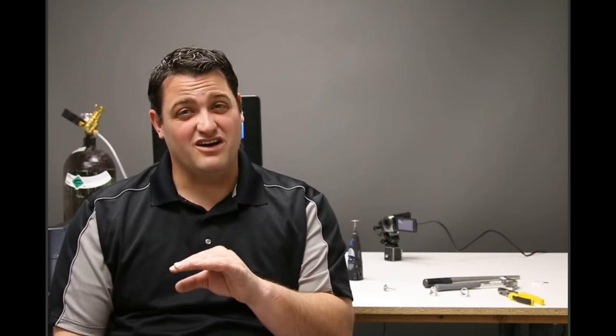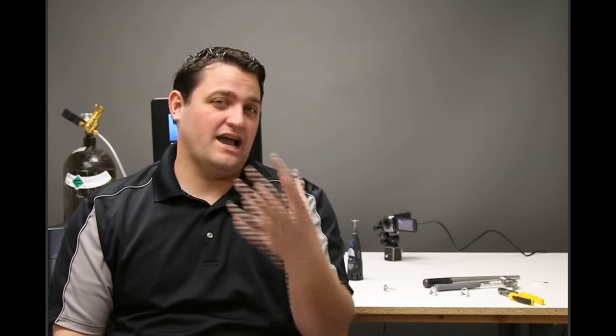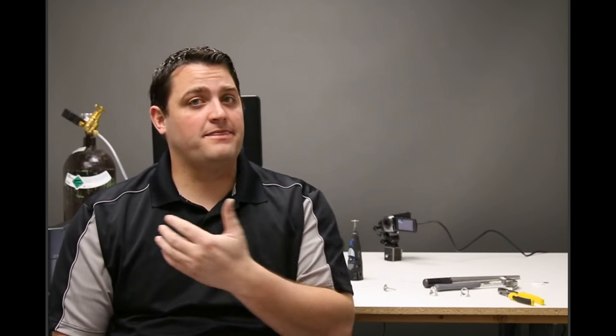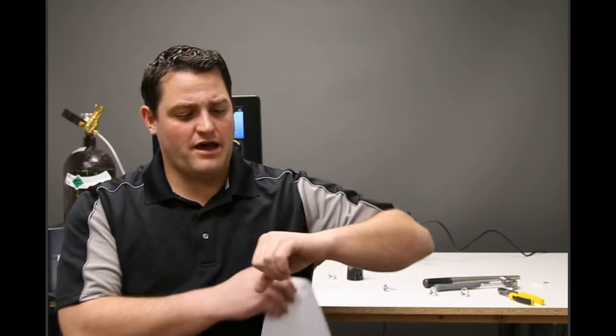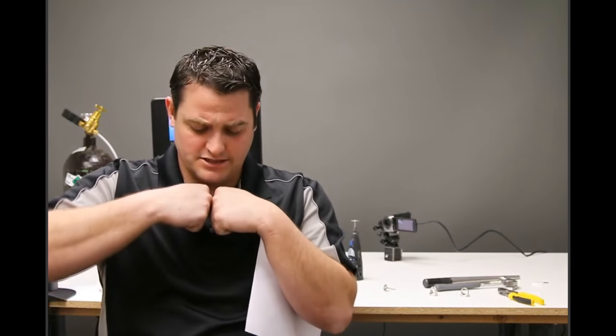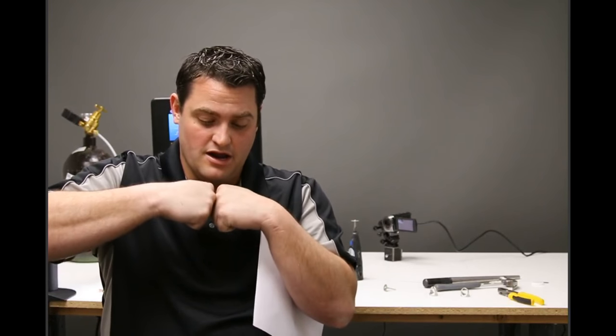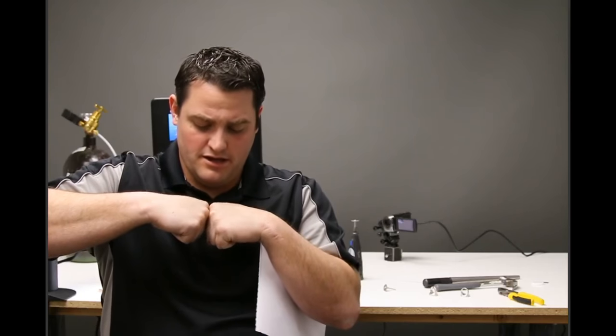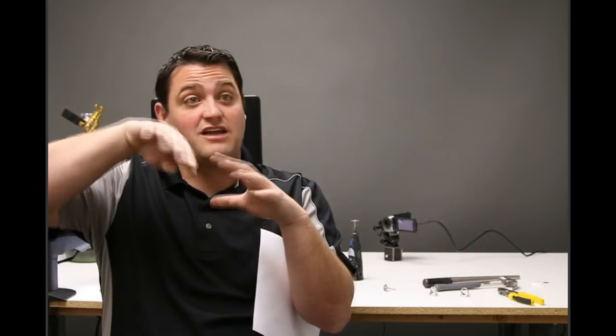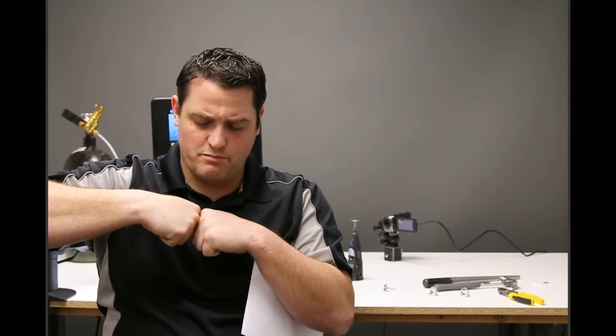But one thing to be aware of is that on the Orion, specifically working with silver, tack mode isn't ideal for silver. Just as we mentioned before, it is very highly conductive electrically, and the welder uses similar principles to a resistance welder. Basically how a resistance welder works is as those two pieces are being pressed together, they don't perfectly line up. The metal at a microscopic level has peaks and valleys. And so those metals don't perfectly line up.